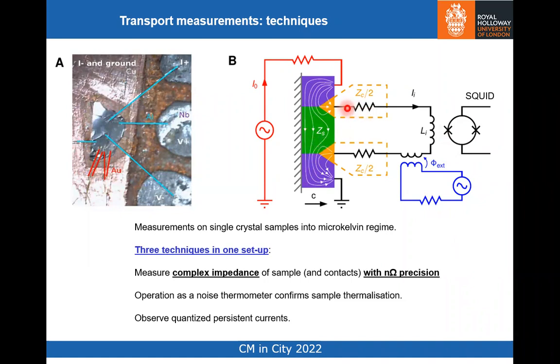There are contacts made by bonding aluminium wires to the sample. And this contact resistance then involves some region at the surface of the YbRh2Si2. So we can measure the contact resistance using that technique, and we can do both of these with nano-ohm precision. And the other point I should have emphasized is that we're measuring the complex impedance, so we can look for inductive terms in the measurement, which I don't think is habitually done in transport measurements on superconductors. That tells us a lot.